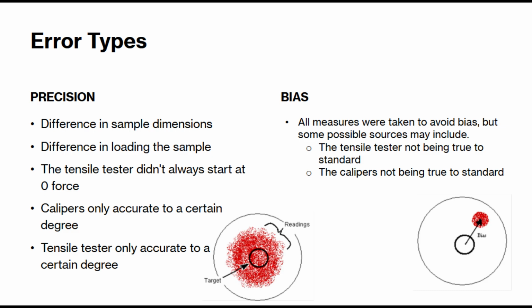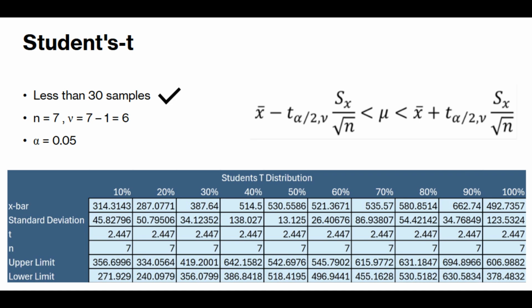While we tried our best not to allow any error to creep into our experiment, we found a few areas in which it might have, the first being in the precision. Each sample had a small amount of difference in its dimensions. We also tried to load the sample in the same way every time, but there could have been slight differences in the way that we did it. The tensile tester, when zeroed, would wander around zero with the force. Our calipers were also only accurate to the third decimal place, and the tensile tester was only accurate to the fourth decimal place. If we had any bias, it came from the instruments not being traceable to the known standard.